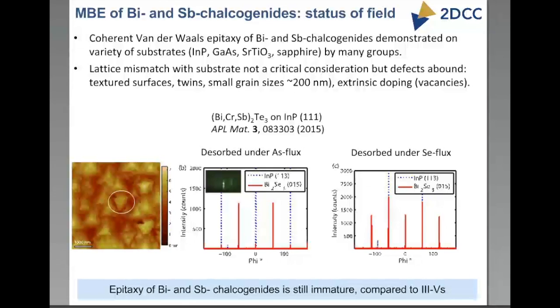So these AFM scans themselves give you an idea that there is twinning. And it turns out that if you look at these X-ray diffraction scans, you'll see that how you desorb the substrate matters. When you desorb the indium phosphide oxide, if you do it under an arsenic flux or a selenium flux, that makes a difference in the kind of twinning that you get. So you can suppress twinning by doing the appropriate kind of desorption. So clearly, the interface chemistry, when you nucleate on these surfaces and so on, does play a big role in what's going on.